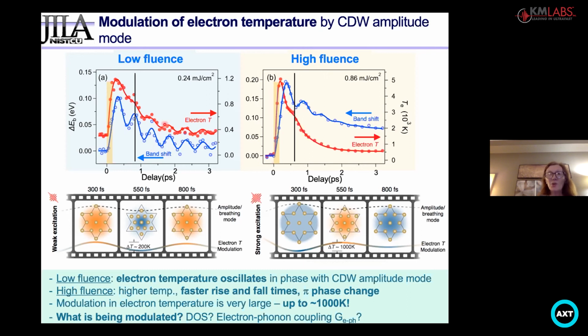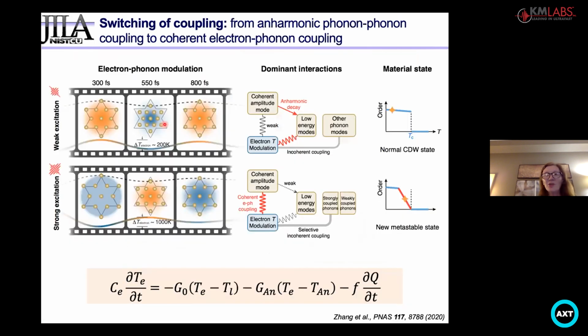And so what we're seeing is that as the amplitude mode is launched, it's modulating the density of states and band structure that is pushing electrons around and changing their temperature. Because the behavior is different when we gently excite the material compared to when we strongly excite the material, we can, just with angle resolved photoemission, learn something about how the phonons and electrons are talking to each other.